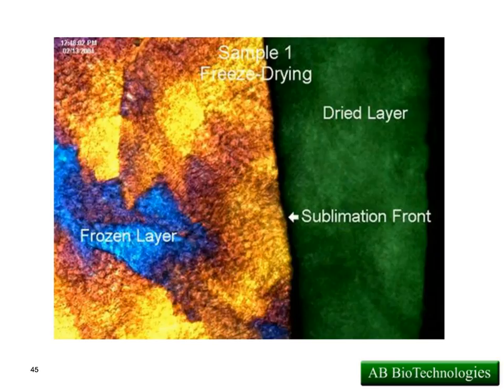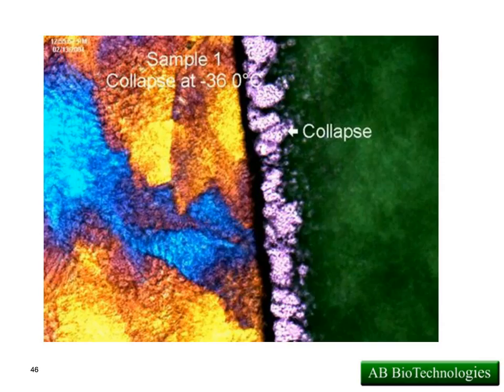And then we just keep warming the sample and warming the sample until we see that sample go through its collapsing event. And we're taking images all along that process as we warm. So we say, okay, at this temperature, we started to see a little bit of collapse. As we kept getting warmer, warmer, warmer, we see the sample totally collapse. So what's going on in here is we've exceeded the Tg'. The interstitial space fluidizes. When we pull the ice out, it can't support its own weight, and we get collapse.